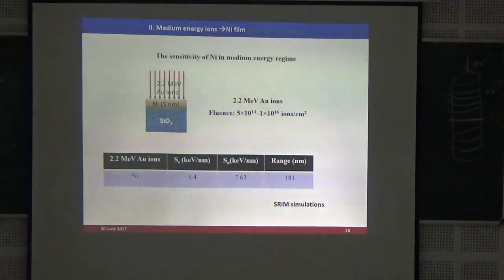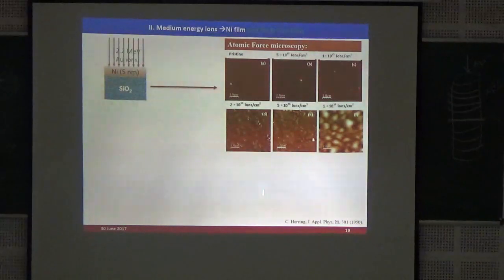Since we have seen nickel as insensitive at the higher energy, in the case of medium energy ions we would like to confirm whether nickel is sensitive to the ion beam in this energy regime or not. For that purpose we have chosen a nickel layer and 2.2 MeV gold ions as a function of ion fluence. And here you can see Se and Sn are almost in the same order of magnitude. These are the atomic force microscopy images. The pristine sample shows nanostructures distributed on the surface. After irradiating these films with gold ions, we see drastic changes with increasing ion fluence. At the highest fluence, we see a mortar-like feature in the surface morphology.